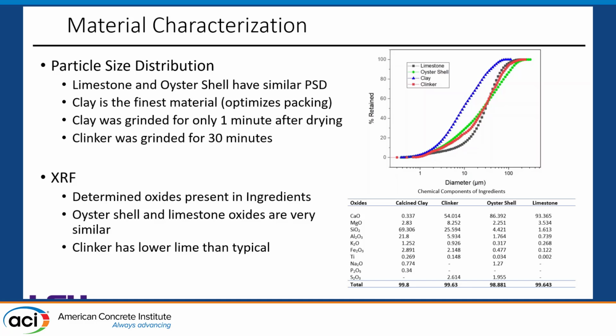For the XRF that we conducted, we again found a lot of similarities between the oyster shell and the limestone. As you can see to the right, for calcium oxide in limestone, it was around 93%, and then for the oyster shell, it's 86%. The oyster shell had a bit more impurities, but of course, that's to be expected. One thing that was slightly disappointing from our XRF analysis was we found that the clinker had a bit lower lime present than you would typically want from a clinker, only about 54% when you really want to see a 60 to 65% range.